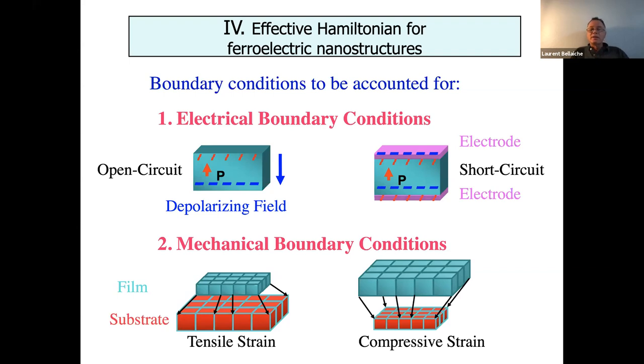If you don't have a screening of the surface-induced charges, you are going to have a big depolarizing field. This is the open circuit electrical boundary condition. If you have something that screens, like metallic electrodes, basically you don't have a depolarizing field anymore. You have short circuit boundary conditions. So in nanostructures, you can go from open circuit to short circuit depending on your system. The second boundary condition that is super important, Osvaldo also talked about that yesterday, is the mechanical boundary condition. If you grow your film on a substrate that has a larger lattice constant, the film is going to expand laterally. This is tensile strain. If you do the same thing but on a smaller substrate, the film is going to contract in the XY plane. We are dealing now with compressive strain. So these two boundary conditions are very important.